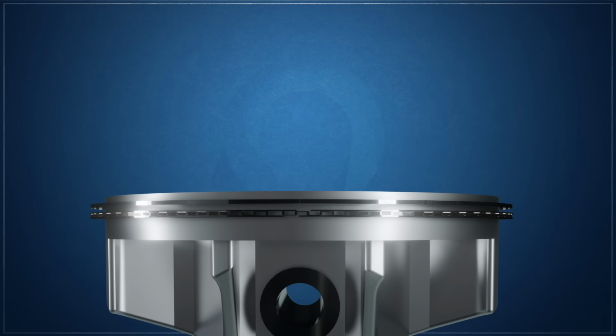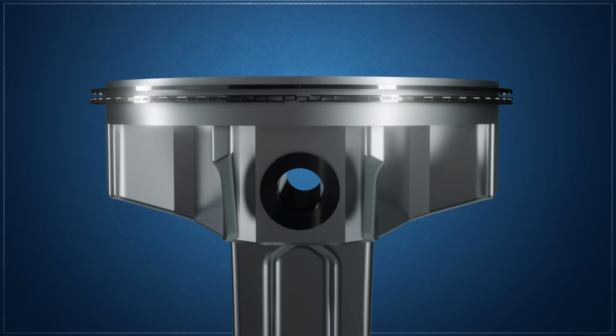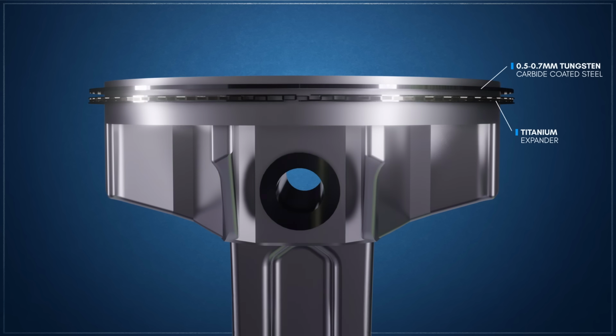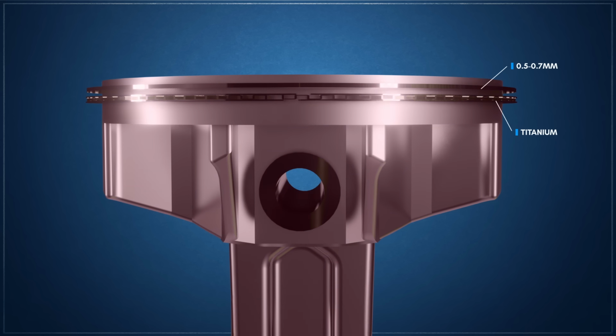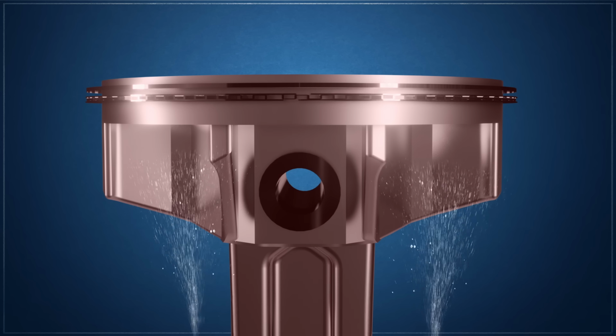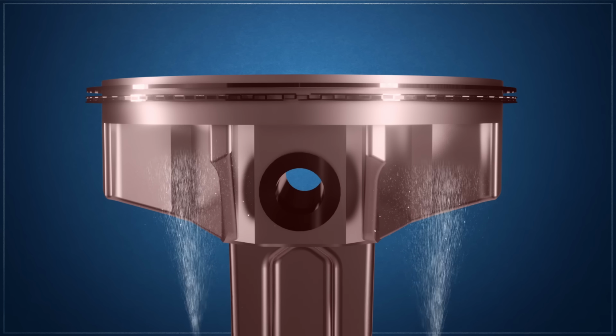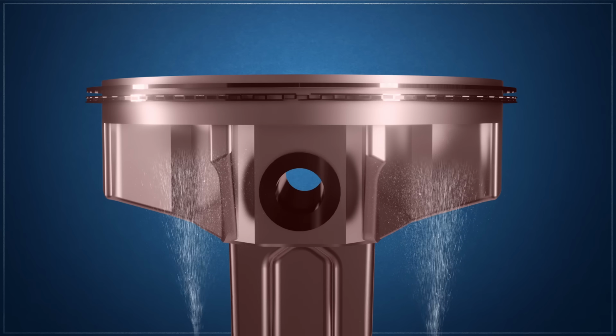On the extreme end of the spectrum is a Formula One engine. Titanium expanders are paired with ultra-thin steel tungsten carbide coated rings that are just 0.5 to 0.7 millimeters thick, with only one compression ring and one oil-control ring. These rings are designed with joint and groove clearances so tight that they do not fully function outside of the engine's operating temperature and require aggressive oil cooling to thermally manage their operation. Their overall operation places the focus on uncompromised gas sealing with minimal friction.